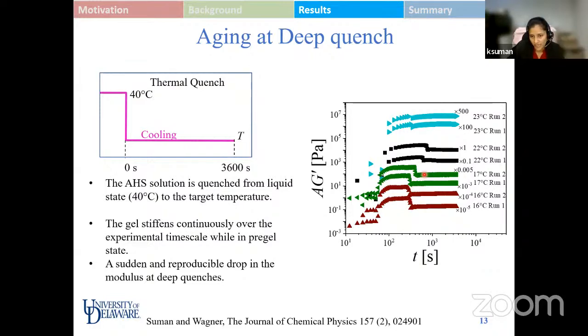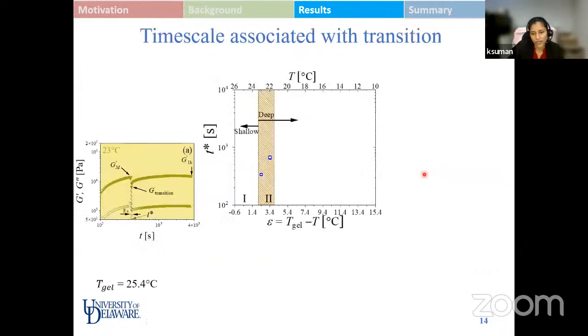quench temperatures as well. So we now go on to have a deeper understanding about what is happening rheologically in the system and what it is trying to say. Initially, when we subject the sample to a quench temperature nearby the gel temperature, let's say 23 degrees as shown over here, we see that at a specific time, the modulus undergoes a sudden decrease, which is followed by a slow continual increase in the modulus value. The sudden decrease is very fast and occurs in a narrow window of 8 seconds.